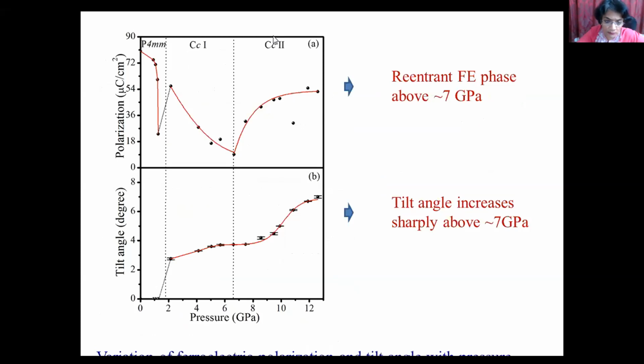Okay, ma'am. So this polarization we found first decreasing, and then it shows a sharp increase, just like at MPB we observed most commonly. In this case polarization decreases with increasing pressure as expected, but above this 7 gigapascal we observe a constant increase in the polarization, which confirms the tetragonal ferroelectric phase.